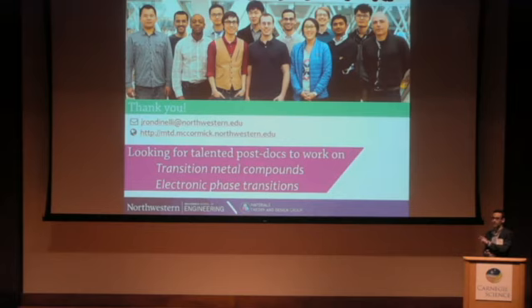In the thin film form, there was no secondary phase of any of these structures seen, and I think that's an epitaxial stabilization effect. But you're right, using traditional solid-state chemistry methods, you do get this polymorphic competition. I have one other question, if I may. If you measure the dipole moment of these things, in general, they're appallingly small. Yeah, the values I showed you here are about 10 microcoulombs per square centimeter, so small, but not nano. Not industrial at this point.